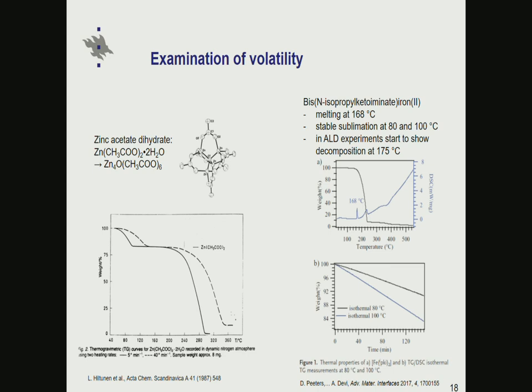Then on this side here, there is an example. This is actually from a paper from Bochum, for an iron precursor, and its TG shows that volatilization starts nicely, but it doesn't go all the way to zero residue. So it seems that there is some decomposition taking place simultaneously with the evaporation. And indeed, in ALD experiments, they saw that this compound seems to start to decompose around 175 centigrades.